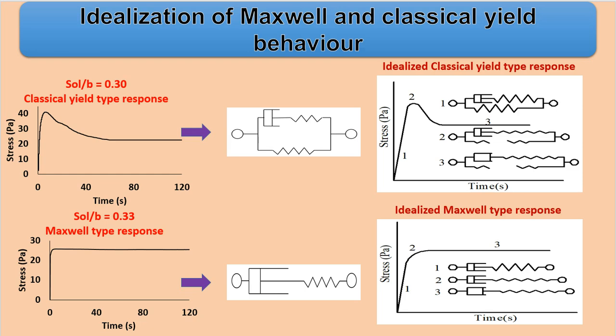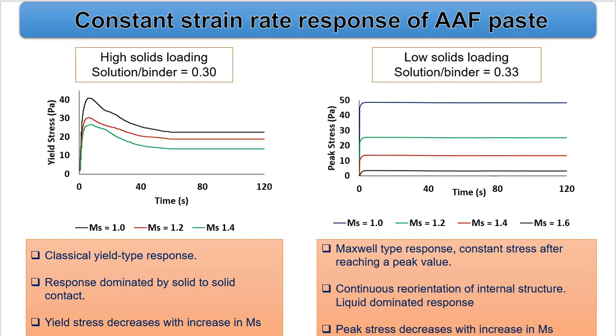In the case of Maxwell type of response, the paste on straining reaches a peak stress value, but there is no breakdown observed, and on continuous straining the material keeps on stretching and carries the same amount of load. In case of high solids loading with solution-to-binder ratio of 0.3, the paste exhibited a yield type of response, whereas in case of low solids loading with solution-to-binder ratios of 0.33, 0.35, and 0.4, we observed only Maxwell type of response.